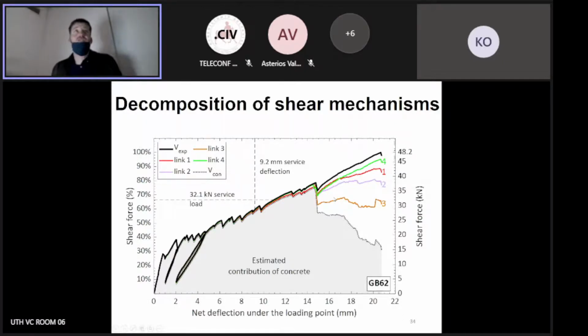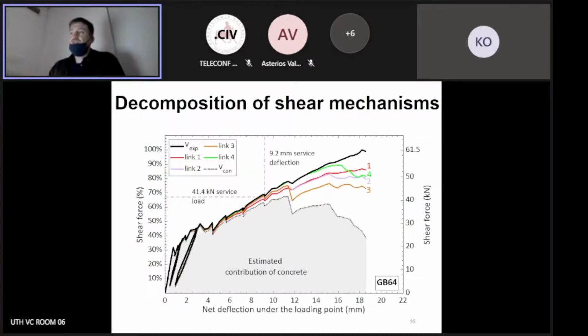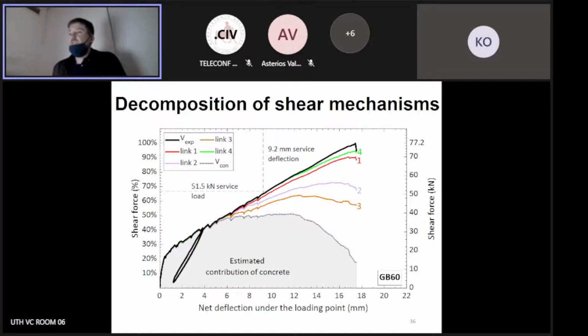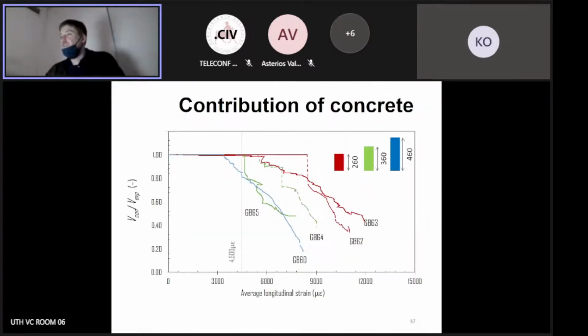This is something that, of course, you don't see in the codes of practice because they assume that the contribution after shear cracking is constant. We don't see this degradation. But the very interesting stuff was that when I compared this across the different sections, I saw that the larger the section, the less concrete contribution, which makes sense because we have larger cracks in larger elements, and we force the shear links to work harder. So although size effects should not really exist in elements with shear reinforcement, you can see that the size related phenomena are clearly present here, which was very interesting actually.